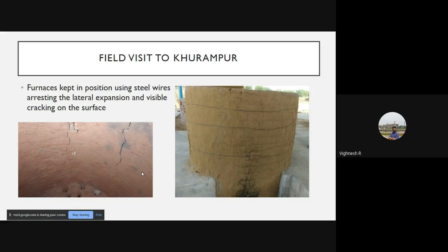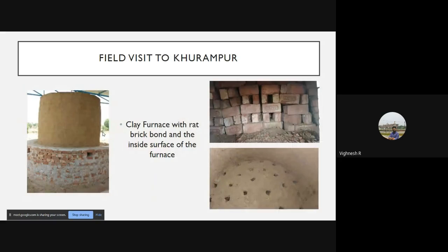But that again proved to be a vital mistake, because we have studied in temperature loading that if we don't disturb anything, if the material is free to expand or contract, there is no stress on it. But if we restrain something, if we put a fixed end on both sides, then stresses come out of that. So natural materials were not a very good option, and this was the second furnace which they made. It was made up of rat-trap bond, which you see over here, and it was actually better than the first iteration. But it could not sustain the temperature, so it required more fuel and reduced in efficiency.